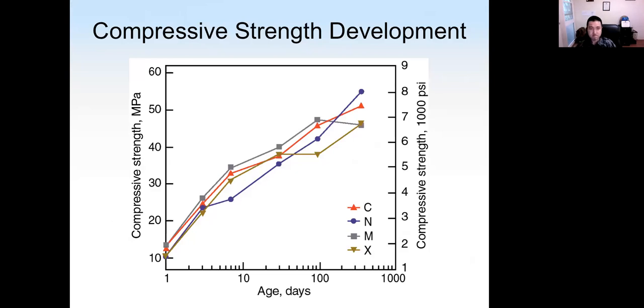This figure compares concrete with different types of superplasticizer. So C is for control, I believe, which is the red line, which means it has no superplasticizer. N, M, and X are concrete with different types of superplasticizer. So basically, we can see the strength does not change significantly depending on what type of superplasticizer we use. That means we do not change the water cement ratio, so keep that in mind. But if we use this to reduce the water cement ratio, we're going to see a lot of increase in strength.